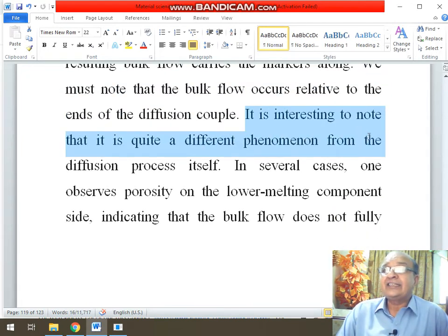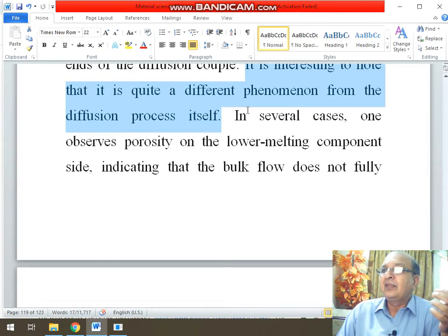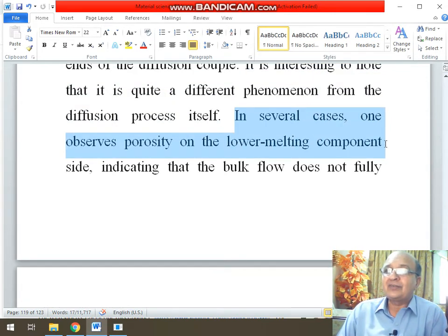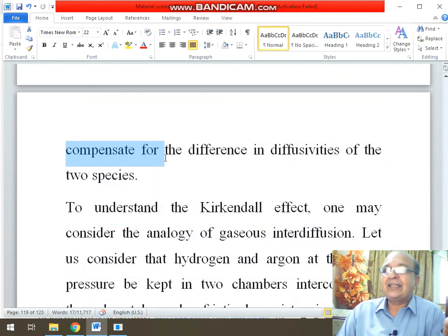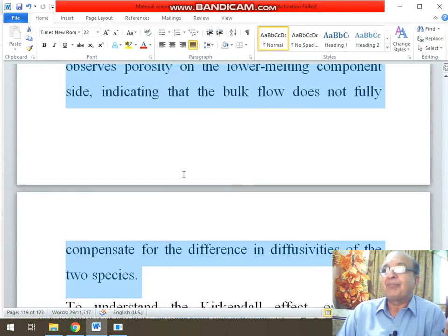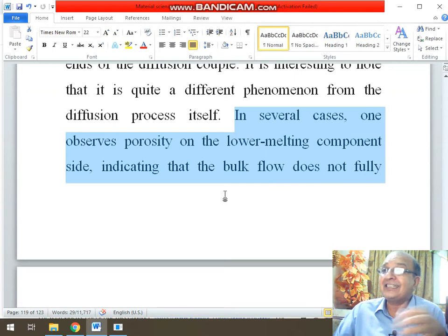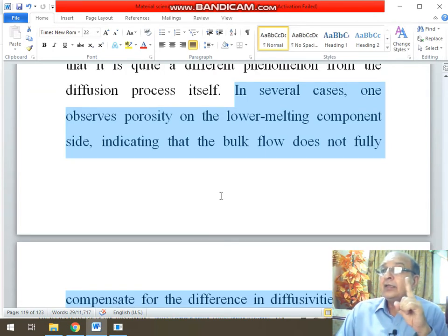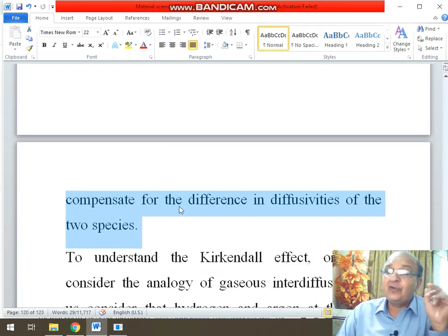It is interesting to note that this is quite a different phenomenon from the diffusion process itself, meaning that in this case mass is being pushed in the opposite direction, which is being compensated. In several cases, one observes porosity on the lower melting component side, indicating that the bulk flow doesn't fully compensate for the difference in the diffusivity of the two species. Where the melting point is lower, more porosity is observed. So porosity also plays a role in the bulk flow.